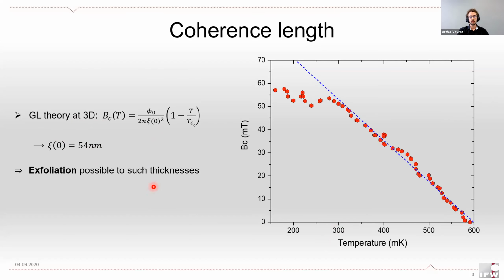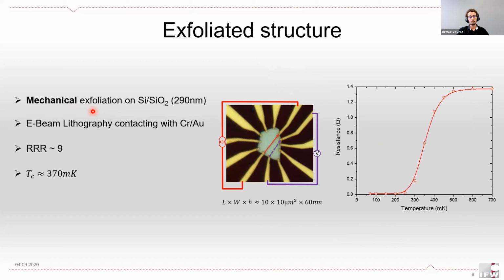So in order to do this, as I said, we mechanically exfoliated our crystals on silicon dioxide substrates. So here you can see the platinum bismuth 2 flake whose results I'm going to show in the rest of this talk. It is about 60 nanometers thick and was contacted using standard e-beam lithography procedures. It shows an RRR of 9, which is lower than for bulk structures, but this is expected since this is an exfoliated structure. Nonetheless, it still shows a nice superconducting transition happening at around 370 millikelvin.